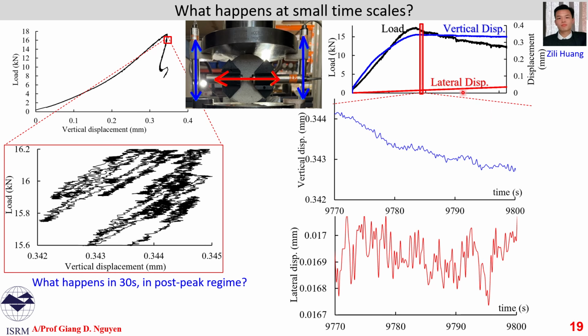2 behavior. The lateral displacement, which is used to control the whole failure process, is going up and down like this, but the overall trend is that it is always increasing, meaning fracture or failure is gradually happening. And the unloading and reloading process on a very small time scale, as you can see here, allows the gradual release of excess strain energy, so that this kind of snapback can be successfully captured.